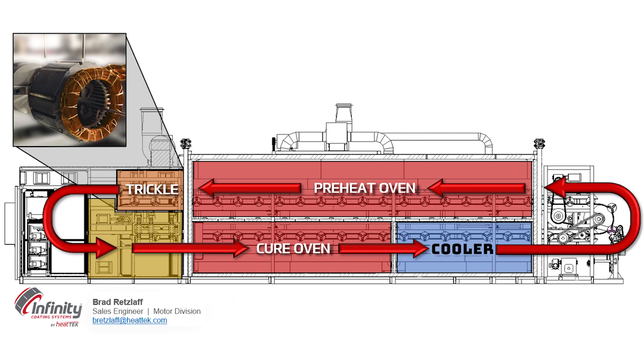After going through the cure zone, the part enters the cooling zone. This can be forced or chilled air. Regardless, a lower bake temperature will provide a cooler part when the stator exits the oven. Overall, ProPreg E240 can reduce process time, increase throughput, minimize odor in the oven area, and eliminate cleanup of the lamination steel when compared to the industry-leading polyester.